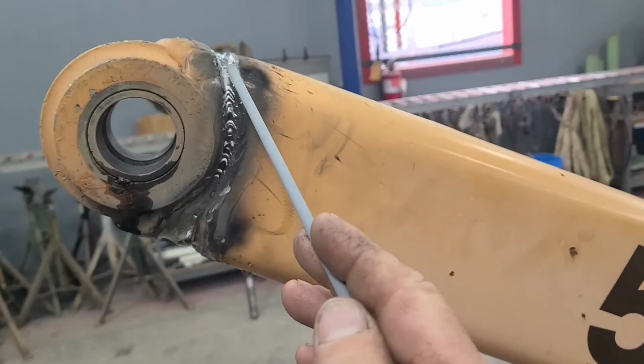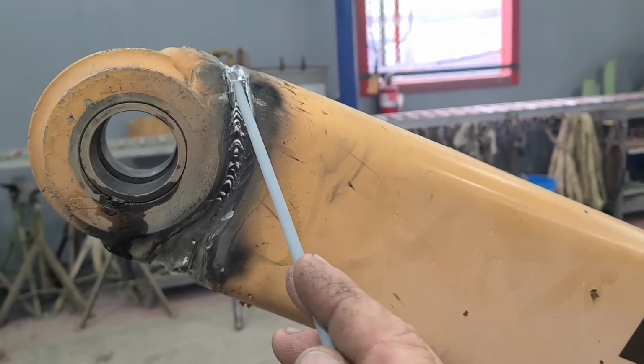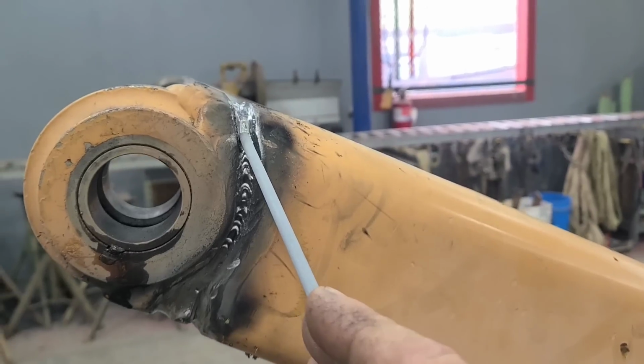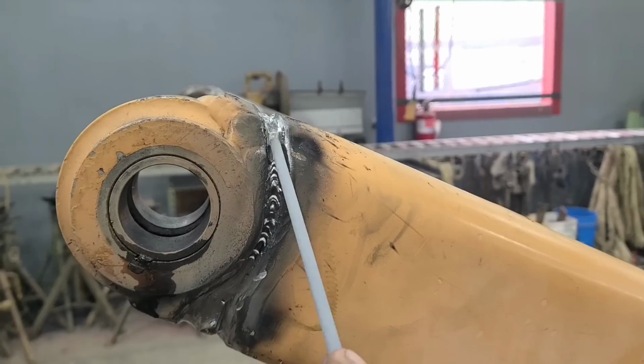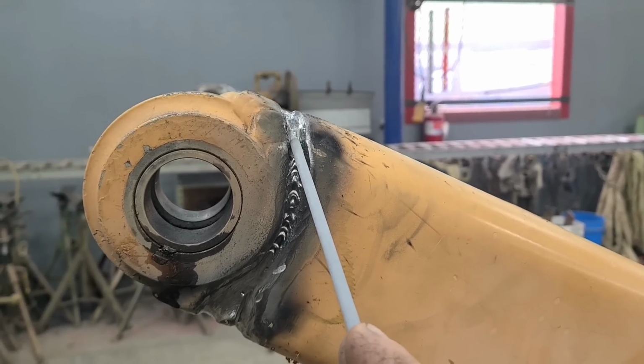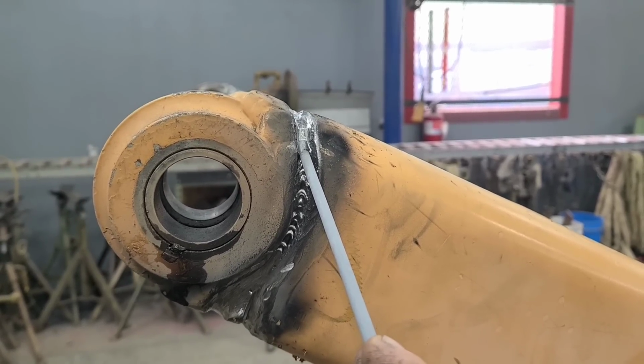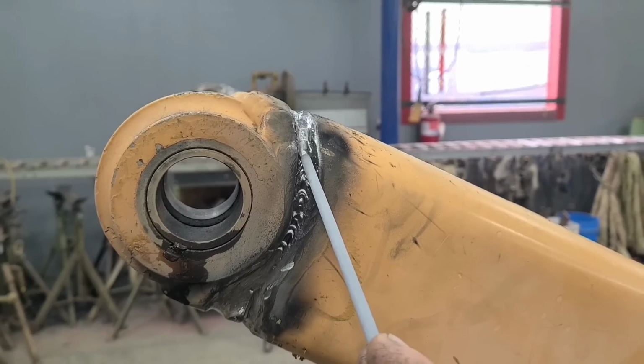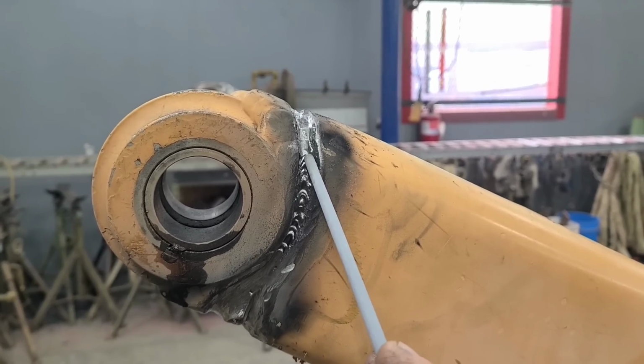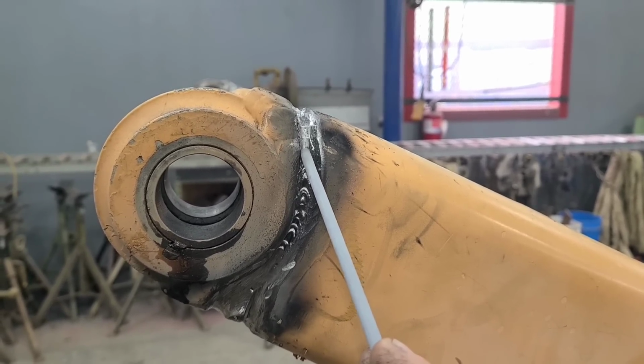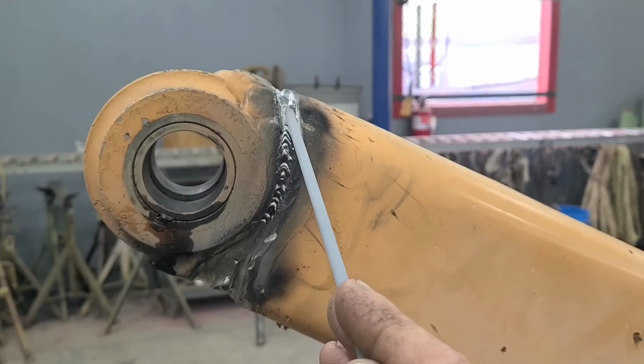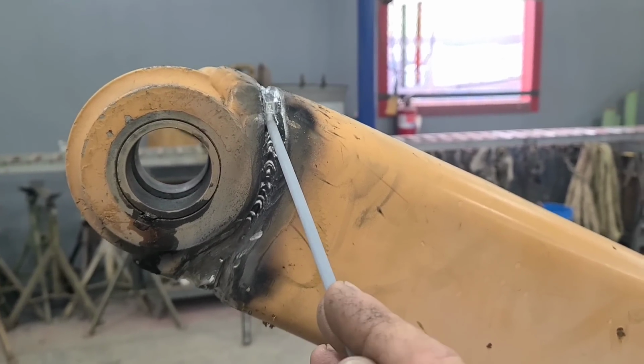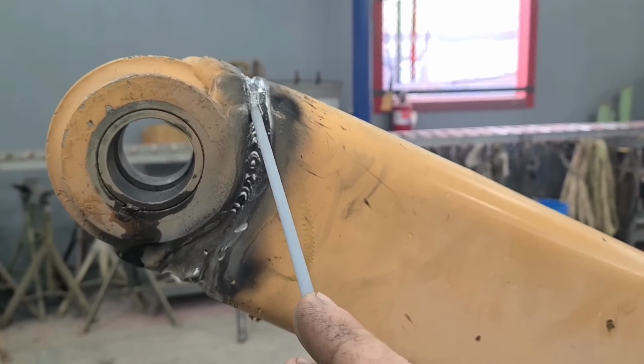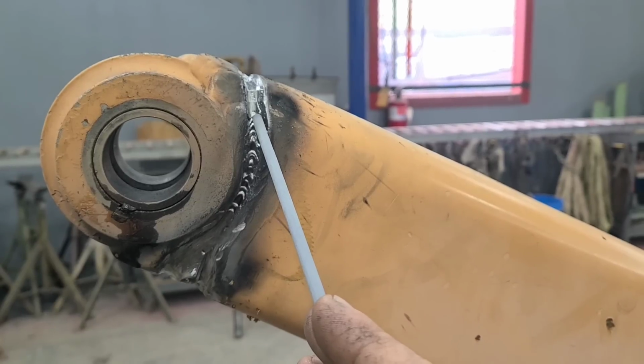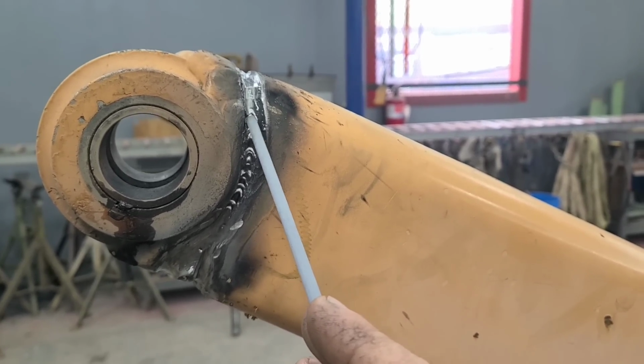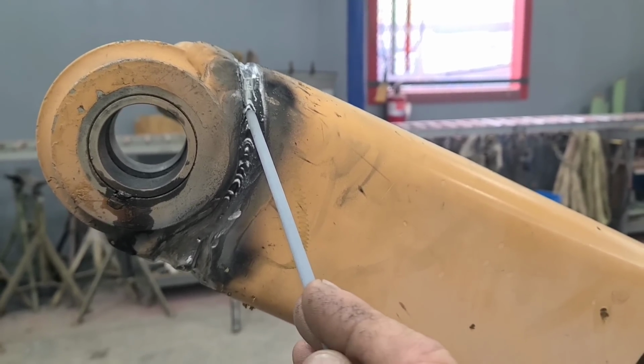What I'm doing in a hot pass scenario with this is I'm checking my arc length by making sure that my rod is making contact with the base metal. And then I scratch. And then I pause. And as I pause, that puddle will swell. And I want it to swell until it's just a little bit wider than the last pass underneath it. And then I scratch. And then I pause. And I let it swell until it's just a little bit wider than the pass underneath of it.